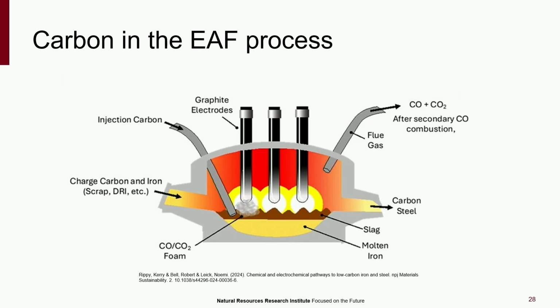So where is carbon used in the EAF? Sorry for those who already know this answer, but I'm going to talk about charged carbon. Charged carbon goes in with the iron materials into the molten iron, and then also it's injected as injection carbon to promote slag foaming. So those are the two spots in the EAF process, and then there's the graphite electrodes that produce the heat that melt the metal down.